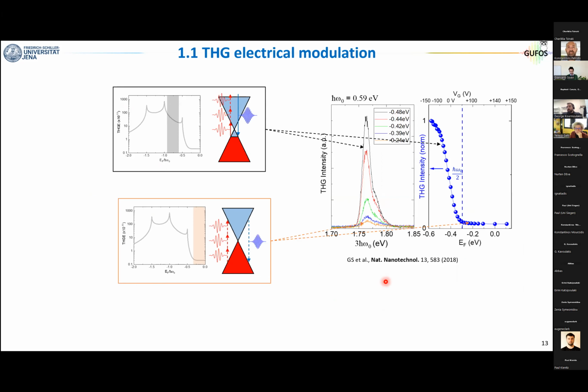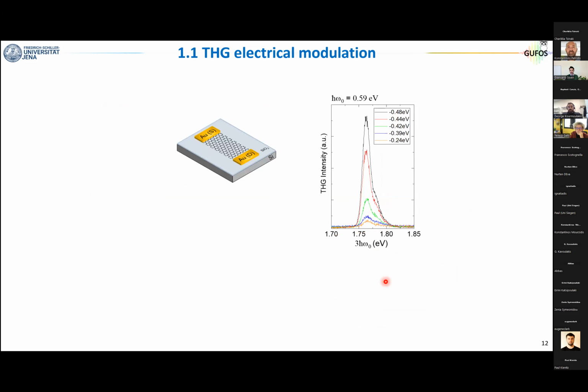And these are the experiments that we did some years ago already. Luckily, this is relatively simple because now you can take a graphene on a silicon dioxide. So basically you build a graphene field effect transistor. You apply a gate voltage. The gate voltage translates into a certain Fermi energy. We fix the fundamental photon energy to 0.6 electron volt. The third harmonic is at 1.8.